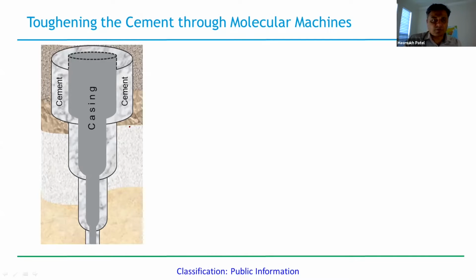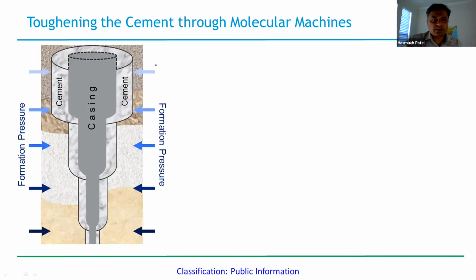So what is happening is, when we go from the surface down to the bottom, the formation pressure is very high. Basically it ranges from atmospheric pressure to 35,000 psi. And the temperature is also very high, sometimes more than 200 degrees Celsius. So we need to make sure that the materials that we put downhole, maybe 2,000 to 3,000 meters from the surface, can sustain such conditions.